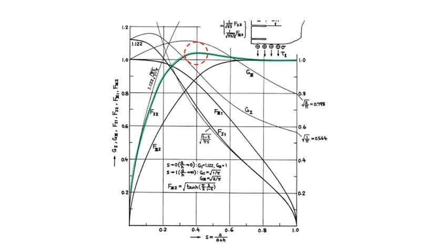So here we have a plot of the solution to the stress intensity factor calculation that's determined by Paris and Irwin. On the y-axis, in this particular format, we have essentially the stress intensity factor, and on the x-axis we have this spacing parameter, A over A plus H. Now, I need to tell you that the way that the stress intensity factor has been defined here is not the usual. It's not done in terms of the square root of the crack depth. In this case, they've manipulated the curve in order to make it the square root of the crack half spacing. And that's a very unusual way to look at it, but it's quite necessary because of the way the derivation plays out.